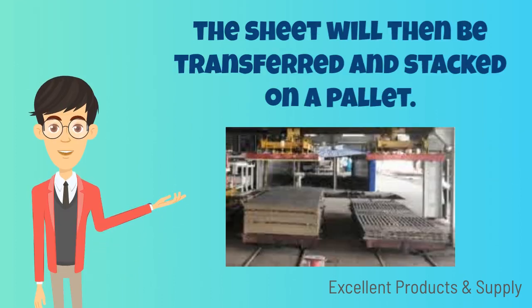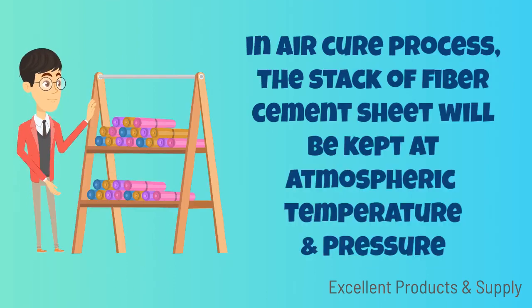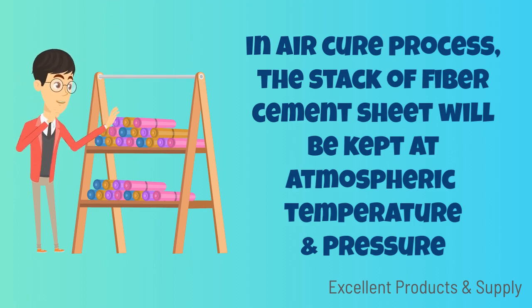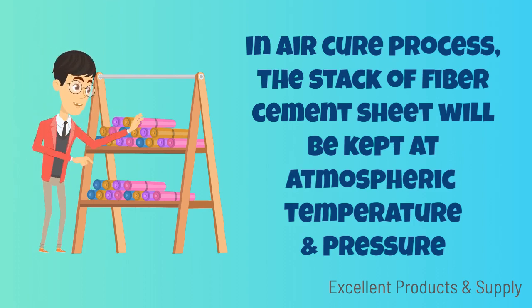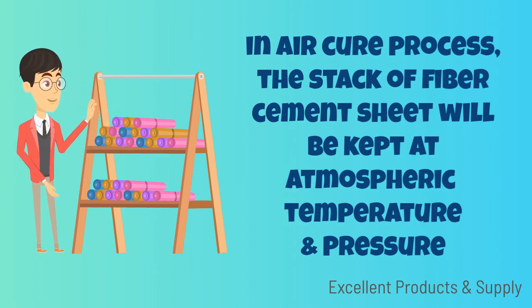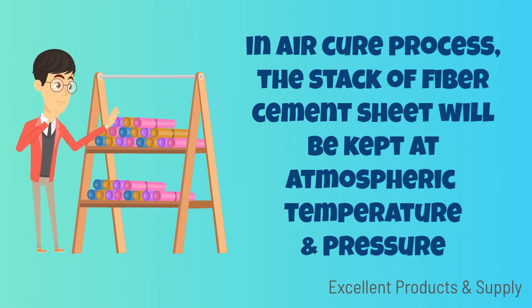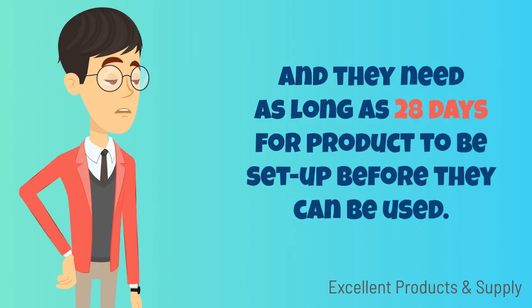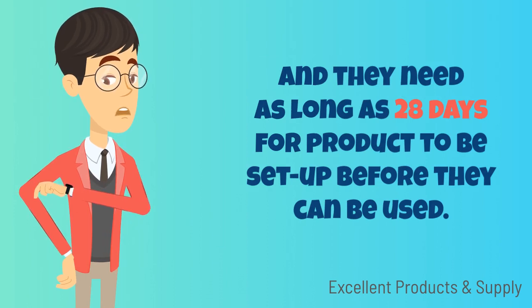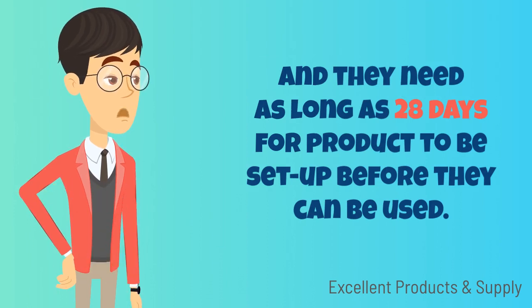The sheet will then be transferred and stacked on a pallet. In the air cure process, the stack of fiber cement sheets will be kept at atmospheric temperature and pressure, and they need as long as 28 days for the products to be set up before they can be used.